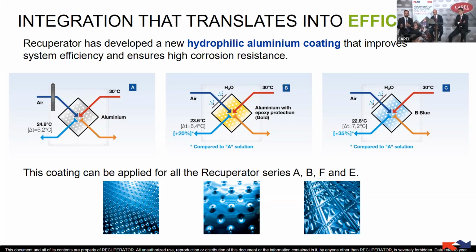The second case instead is with the humidification system that replaces the wet pad with the pressurized system that is going to spray, so humidify the air at the inlet and also inside the heat exchanger. So the heat exchanger has to be wetted. But we can do something more. If we replace the heat exchanger with a standard epoxy protection with a special coating like hydrophilic aluminium coating, we can increase the wettability. So the second key that I've said before, the wettability of the plate, enhances the cooling capacity of the whole system.